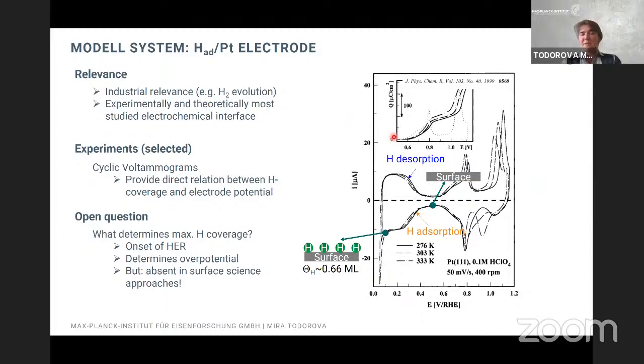You have already seen cyclic voltammograms throughout this conference. So this is a cyclic voltammogram for the platinum water system. And what was our interest? Within this region, you see the potential of zero charge, so basically just the bare platinum surface in contact with water. Along this branch, there is hydrogen adsorption. Along this branch, there is hydrogen desorption. And you see that it seems to be extremely reversible. What was also interesting for us is that there seems to be a maximum coverage that can be reached with hydrogen adsorbed on the surface, which is around 2/3 monolayer coverage, and afterwards hydrogen evolution sets in.